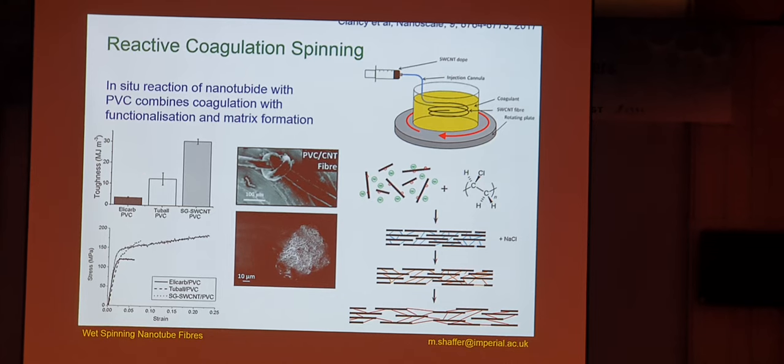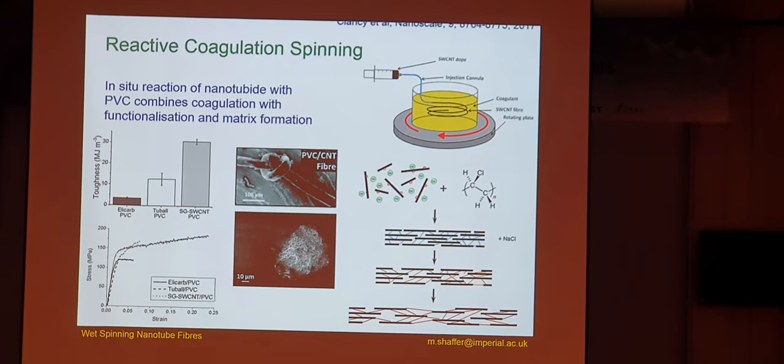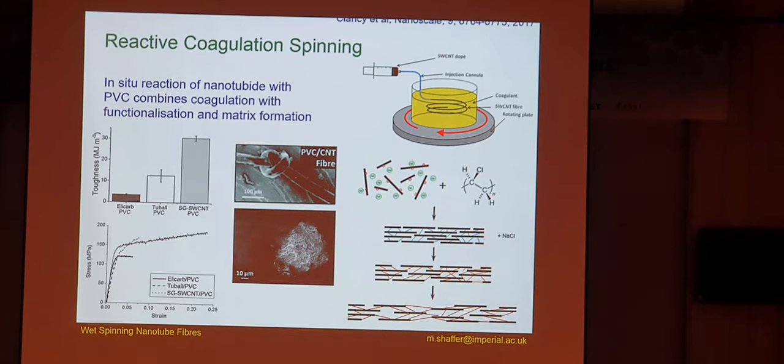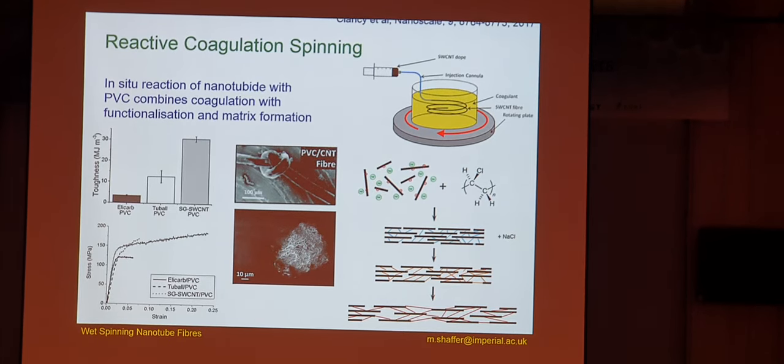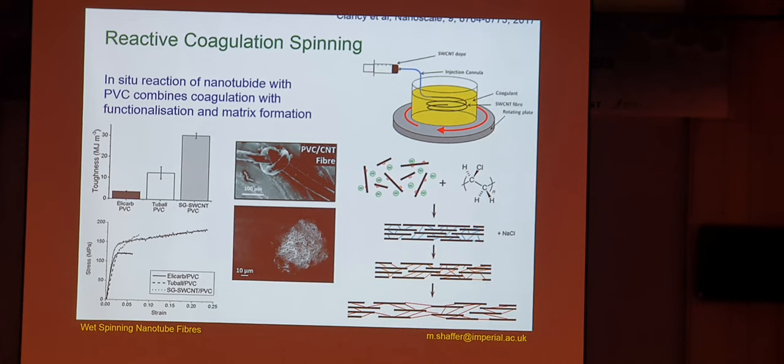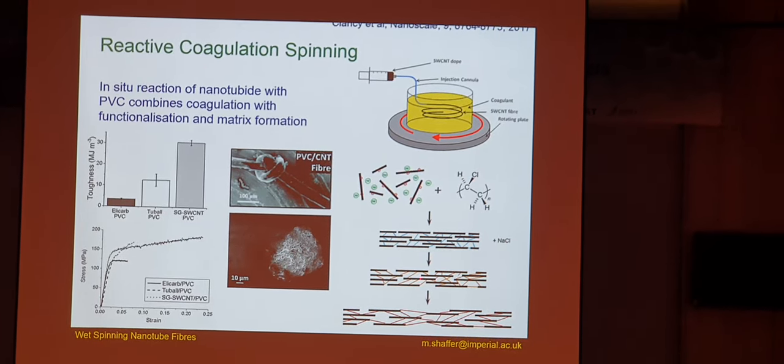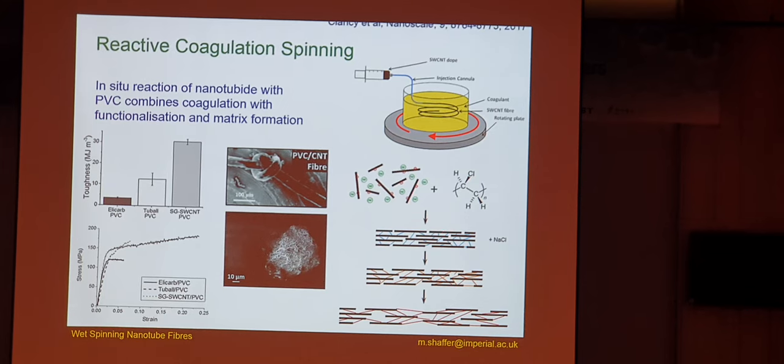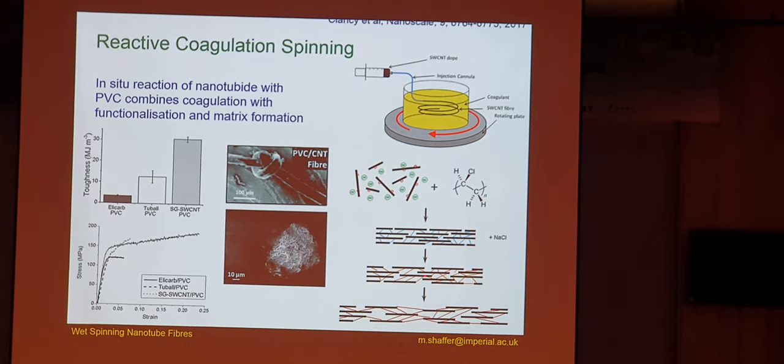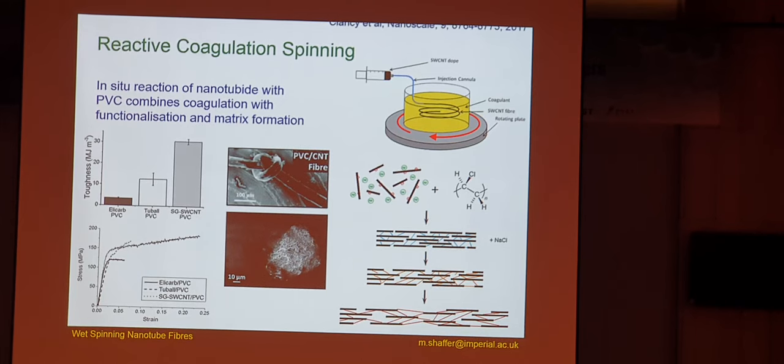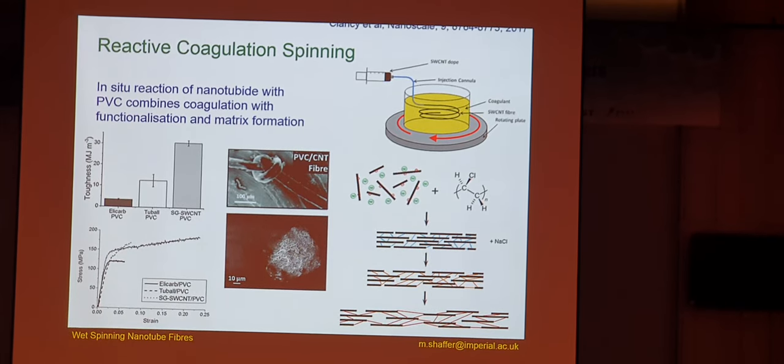We tried with a range of different aspect ratios and found that as you increase the aspect ratio of your nanotubes, you increase the strength at failure and you increase the energy absorption and toughness. One question about why you might not have better properties is that this is quite a disordered network. The nanotubes are not as aligned as in my little cartoon. And also the connections between the nanotubes are all different lengths, and so not optimized as you begin to strain the fiber.